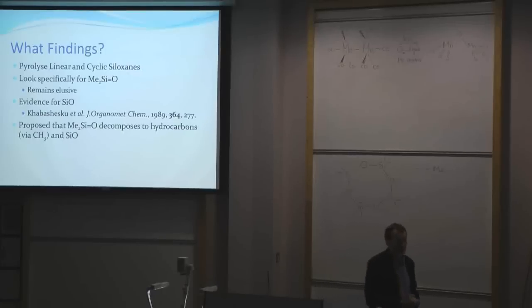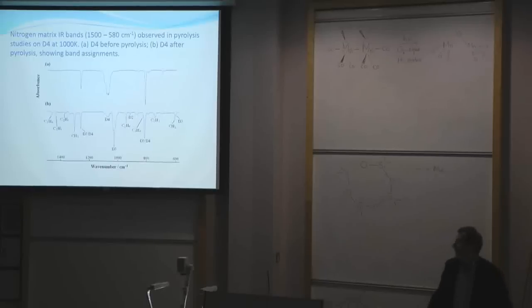You get a small amount of silicon monoxide, and you get a mixture of hydrocarbons, which, if you think about the possible mechanisms, and you have a reasonably imaginative theoretical chemist to work with, you can understand how you can make these different hydrocarbons from the methyl radicals. So we looked at that type of work, and these are the sort of spectra you get if you heat these up. You could see that a whole range of hydrocarbons are being produced there, CH4.